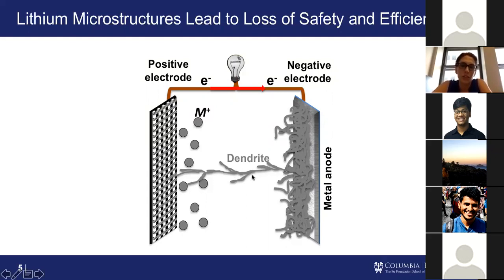Whenever it grows in these dendritic-like structures, they are very sharp and they can pierce the separator. And what that means is whenever they pierce the separator, they can cross over, connect to the positive electrode, and cause a short circuit. That obviously causes the cell to die. So this is no longer a functioning battery if you don't have a separation of voltage between the positive and the negative side. But another thing that happens is you'll notice in this cartoon, I have it drawn with a very high surface area. So this lithium is very fluffy on the surface.